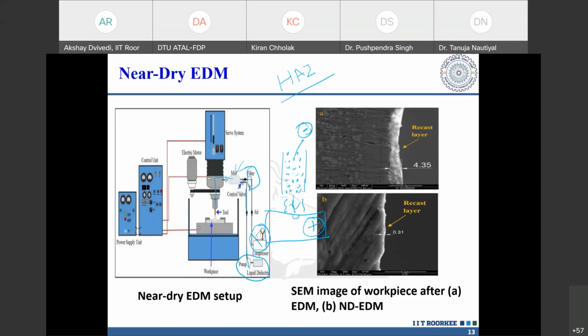The surface quality is around 2 to 3 times better with near dry EDM as compared to the conventional one. What happens with the fumes? What happens with toxicity? What happens with recycling? The amount of liquid that we use here is very less. The flow rate is around, let's say, 1 ml per minute. Usually, whenever you do machining on EDM, you use it for maybe 5 or 10 minutes for a particular job. So in 10 minutes, you will be using only 10 ml of that fluid, and that too is atomized. The fluid we are referring to is water, or it can be glycerin.